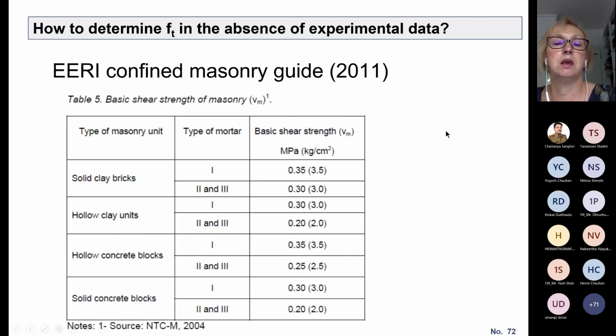And these are some values of the maximum shear stress. You can see it is around 0.2. That is from his testing. In the confined masonry guide by EERI, which I mentioned yesterday and suggested that you download, we can also share it if you haven't downloaded it, there are recommended values based on Mexican experience, and the suggested value for the lower strength mortar, which I would expect in India, is around 0.3.